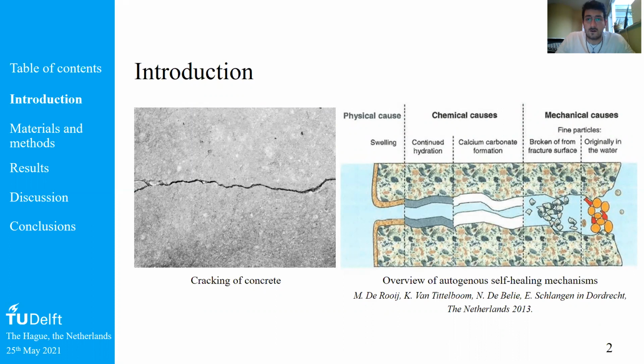But luckily, there are cracks that are not that dangerous for the service life of our infrastructures, because concrete has this autogenous capacity to self-heal cracks physically, chemically, or mechanically. For example, through continuous hydration of unhydrated cement particles and through carbonation of the matrix and precipitation of calcium carbonates that can fill up cracks.